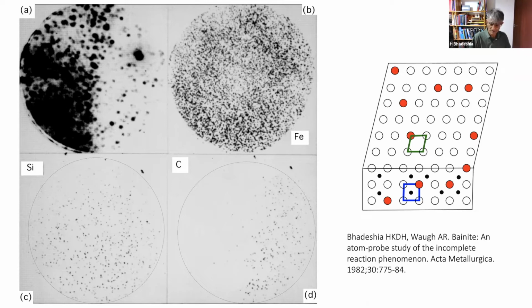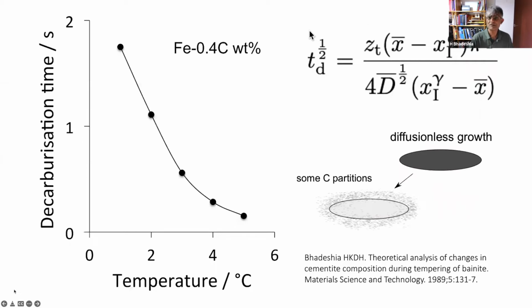into the austenite. Now, at the time, I happened to be working with a central electricity generating board in Britain on sabbatical, and my task was to define a microstructural change that could be used as a time temperature indicator so that we can assess the remaining life in power station components. And I derived an equation for the chromium concentration of cementite as a function of all the heat treatments and cycles that turbines go through. And that equation is exactly the same as for describing bainite growing without any diffusion, but partitioning carbon after the event.